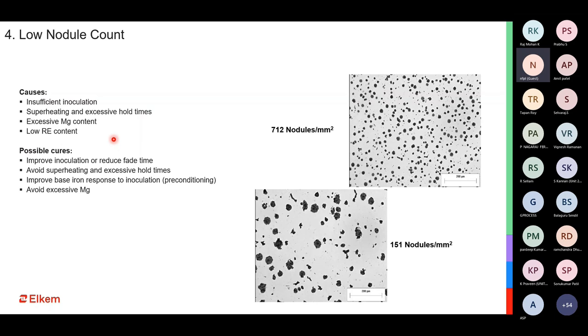One of the causes, like I mentioned, for poor nodule count is the insufficient inoculation, superheat and excessive holding time. So when you have a much higher superheat, in that case, you would get a poor graphitization and thereby a poor nodule count. You can have excessive magnesium content. Magnesium is an anti-graphitizer. We all should be knowing that. So higher the magnesium, better it is not the case. You should have lowest possible magnesium and best possible nodularity. Any excessive magnesium is a strong carbide promoter and a strong anti-graphitizer. And therefore, if you have a higher magnesium content, you will get a poor nodule count. And of course, if you do not have sufficient RE, means you are not able to take care of the trace elements, which are again anti-graphitizers, and that is why you get a poor nodule count.